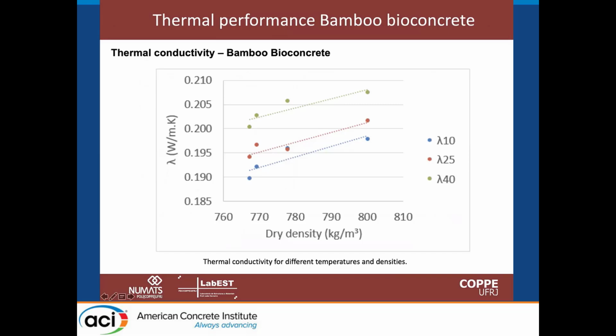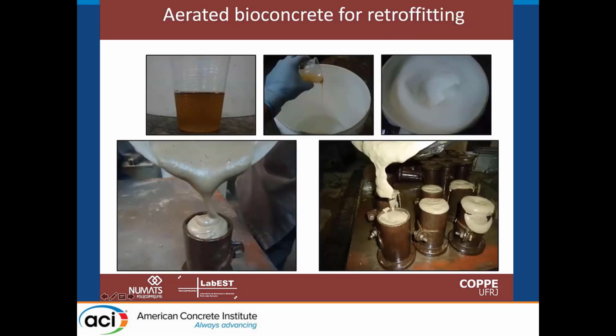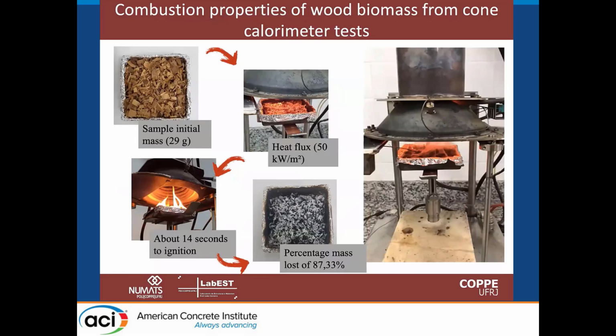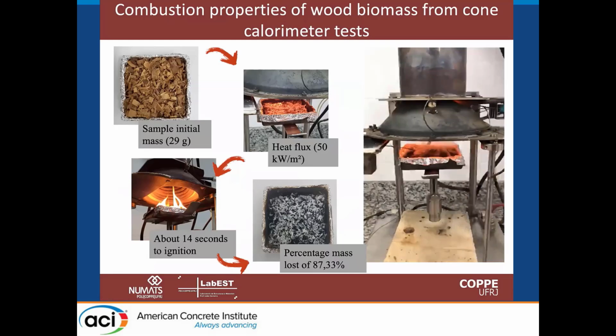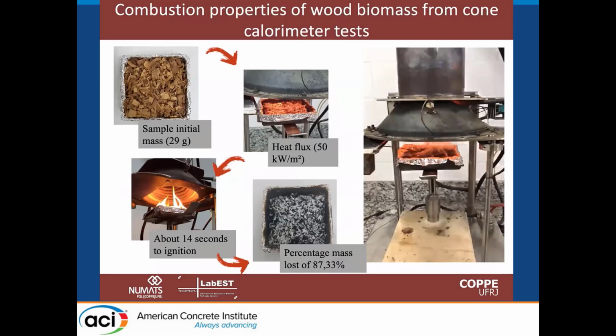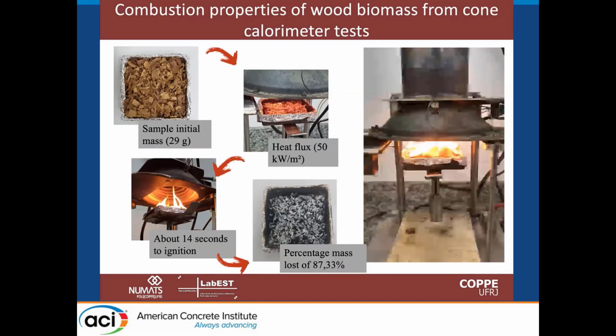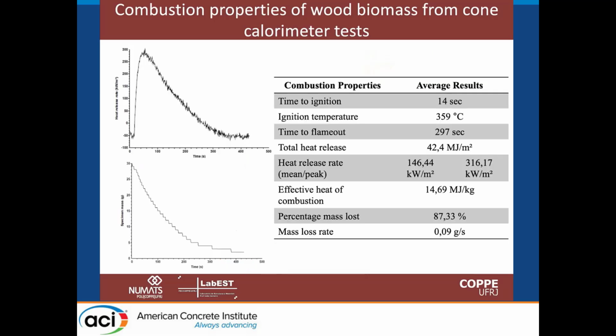So they can be used to improve the thermal efficiency of buildings. If we need an even lighter material, we can also aerate this bioconcrete, making it even lighter, and then we can reduce even more the thermal conductivity. We tested, of course, these materials; they are sensitive to heat flux. We did some calorimeter tests to see the number of seconds the biomass ignites. But when we use up to 75% of this biomass in the cement matrix, the cement protects the material and